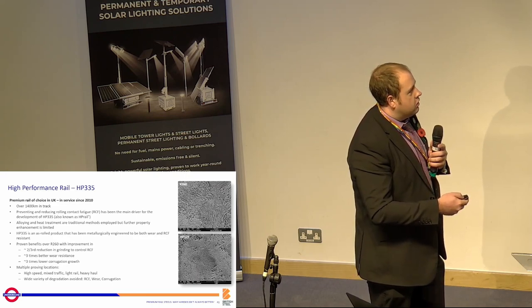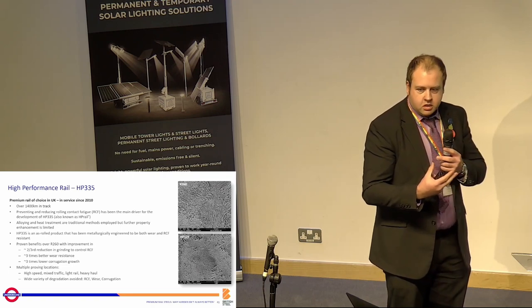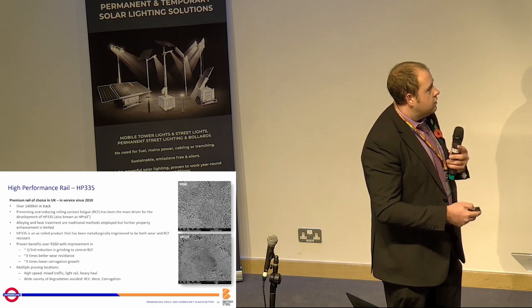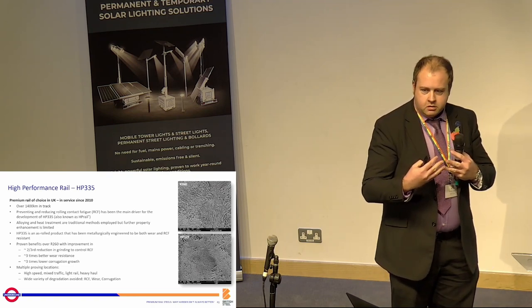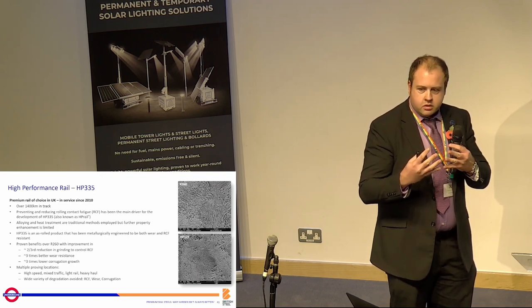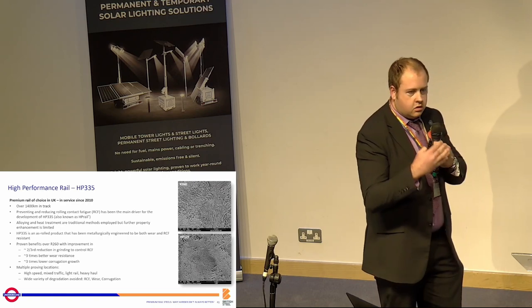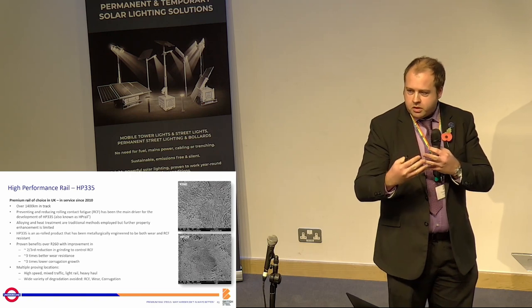These white bands that you see here are called ferrite, and they're more or less pure iron. They're combined with these dark bands here, which are cementite — a combination of iron and carbon in a compound. The way this works and what gives rail its unique wear properties is these two phases of material work together a bit like yin and yang, giving you the best properties of the rail. With HP335, we get a finer spacing between those two compounds, giving it a lower wear rate and greater resistance to RCF.